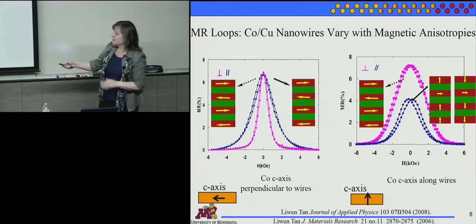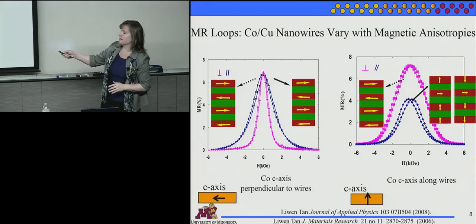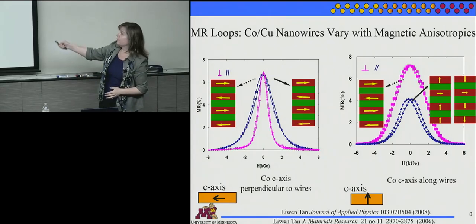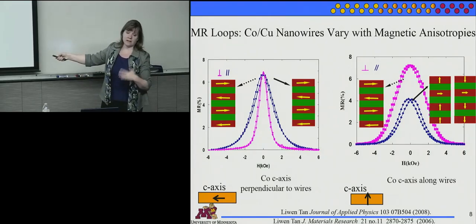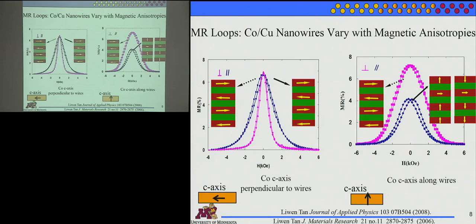And there's a little more to it because also if the spacing here is different, that's going to also favor an anisotropy along the wire. But basically, you can see the difference in the magnetoresistance because you're sensitive to the current along the wire. And if we're making domains by magnetizing it parallel, and those domains, well, you have a closed loop here, so they're happy to stay. You have less scattering at those interfaces, so we don't have as high a resistance at the remnant state because we don't go fully back to antiferromagnetic.